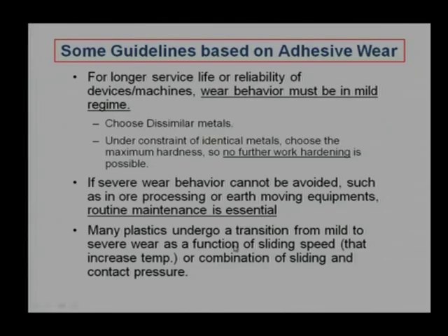The last guideline says to try to load components below their transition limit. We know the transition limit comes from the load point of view: beyond a certain load, there will be a jump in wear rate, which was shown in one of the slides in the previous lecture. Well, in this case, we are talking about temperature. Polymers, plastics or elastomers change their behavior with temperature. Of course, all materials change behavior with temperature, but polymers are more sensitive compared to metals and ceramics. So, we are emphasizing plastic in this case.